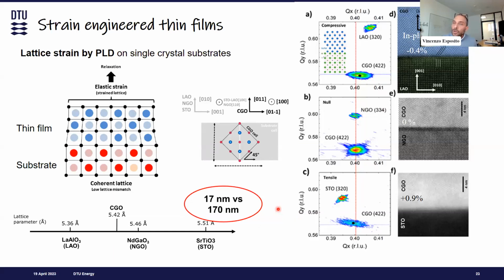And now we can actually tune the strain to be either compressive, tensile, or we can even choose a substrate which gives no strain at all. On the other hand, when we go for a thick film, these are supposedly completely relaxed, and this is also what we see from our XRD, from our diffraction characterization.